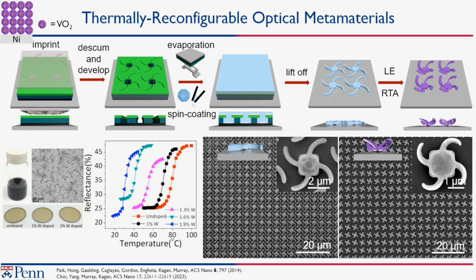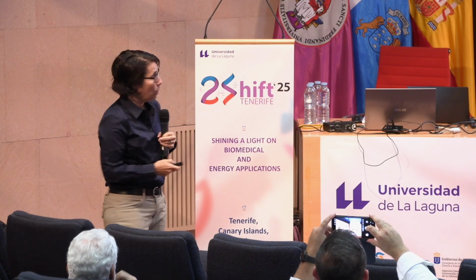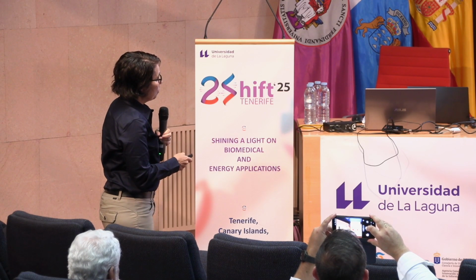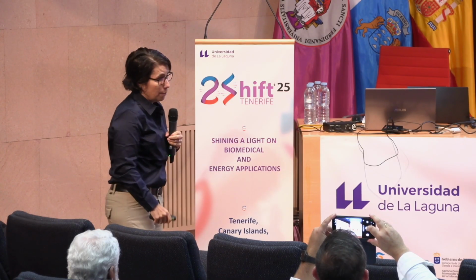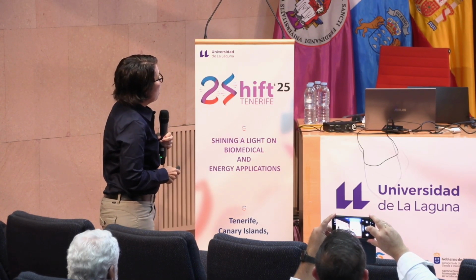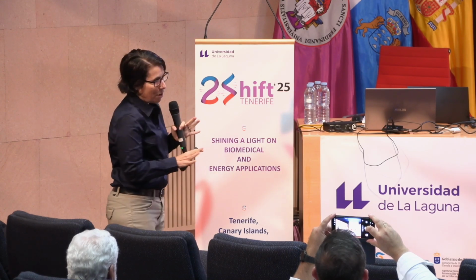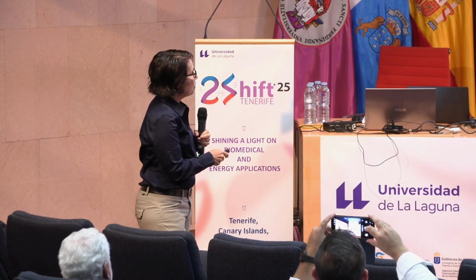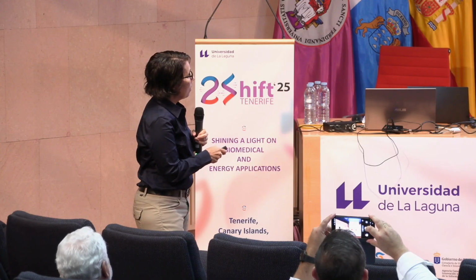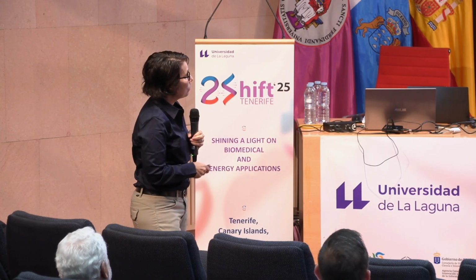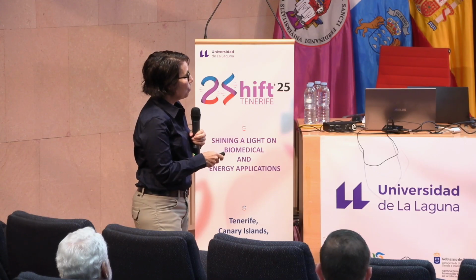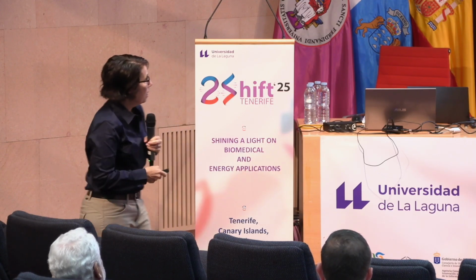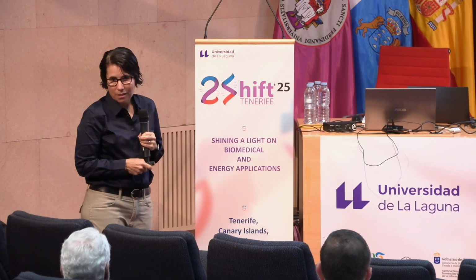And you can tailor that phase transition by controlling also the doping of the material. So you can do that in the synthesis pot. In a moment, I'll show you can actually do it after synthesis as well. But if you introduce dopants, you can just tailor the temperature at which the transition occurs. And so what we do is that we, again, do the same process. We can imprint onto the surface. We can deposit a metal, then deposit the nanocrystals, and then we can both do the ligand exchange and anneal it in an RTA, and we can make VO2-based metamaterials.